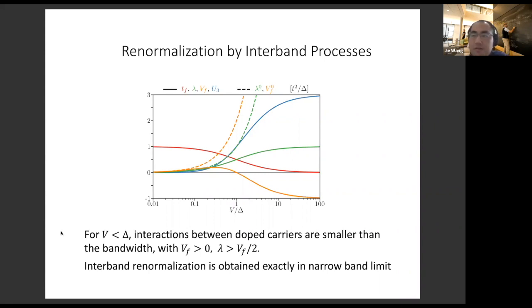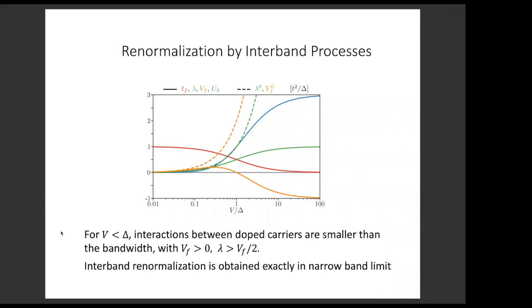Sorry, I lost you after you said the solid line is exact in the Schrieffer-Wolff transformation. Yeah. Okay. So the exact transformation shows that the effective interaction strength deviates strongly from the direct projection, and in particular, we see that the ratio of the correlated hopping lambda and the density repulsion exceeds 1/2. Okay, exceeds 1/2.